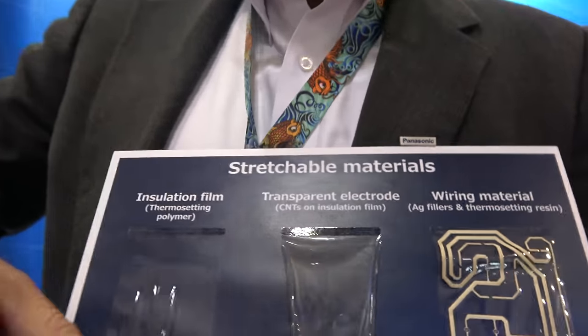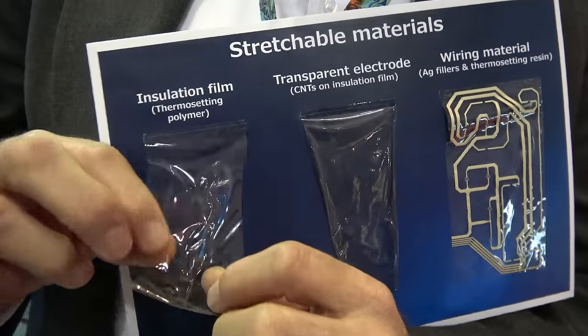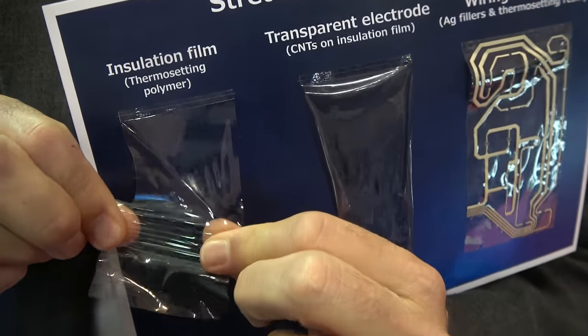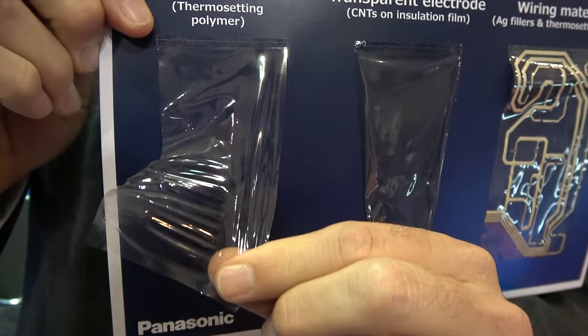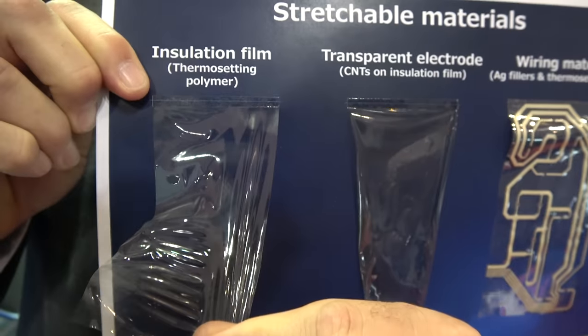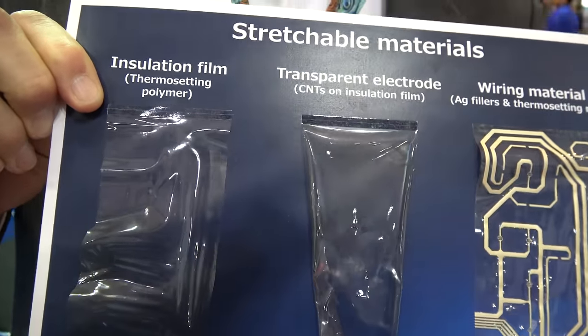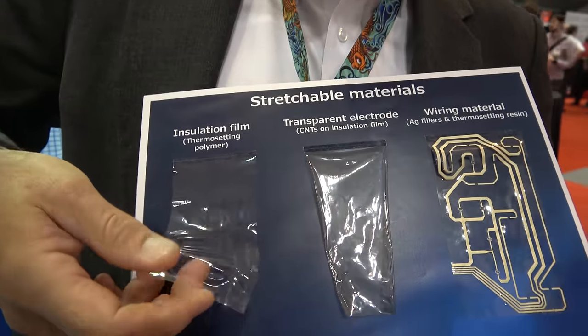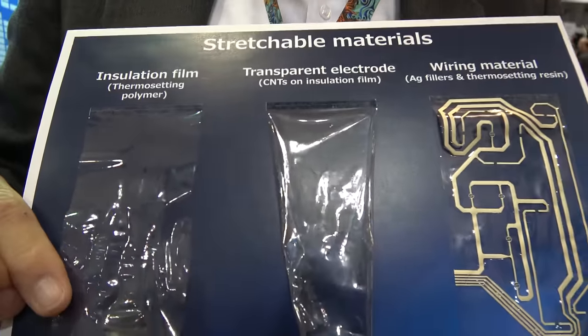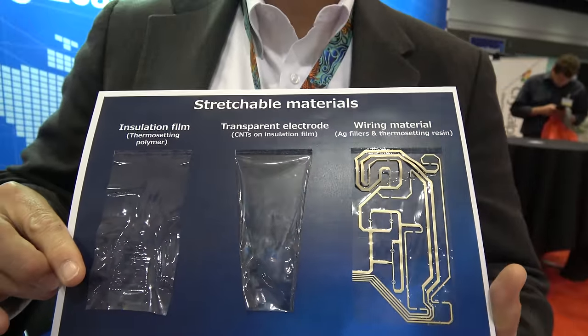The base film is 50 microns thick and can be made from 25 to 150 microns. Most uniquely, it uses thermosetting chemistry — not thermoplastic — giving it high temperature and chemical resistance. Because it's stress-releasing, it slowly relaxes over time and returns to its original shape with virtually no hysteresis.